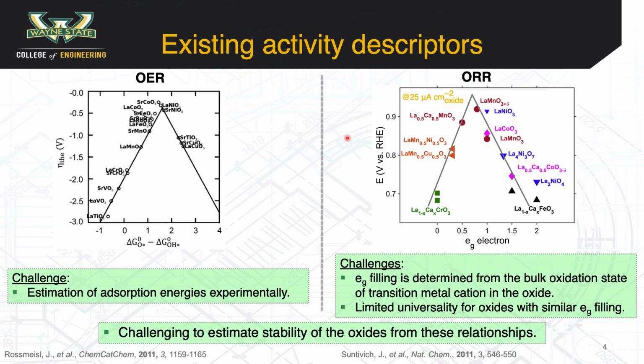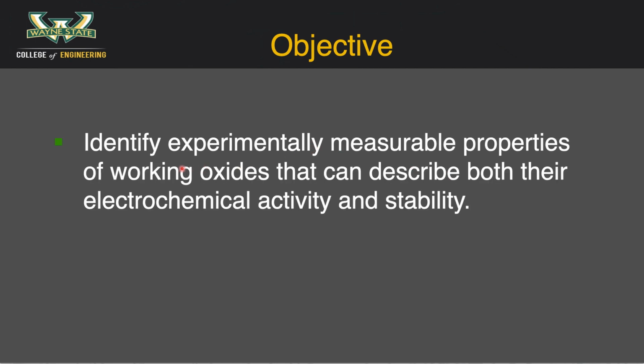One common theme between the two descriptors is the fact that both mainly study the electrocatalytic activity while providing limited insights into the stability of the oxides. With that, we set off by asking the following question. Is it possible to identify experimentally measurable oxide properties of working oxides that can describe both their electrochemical activity and stability, while using the oxygen reduction reaction as a probe reaction?